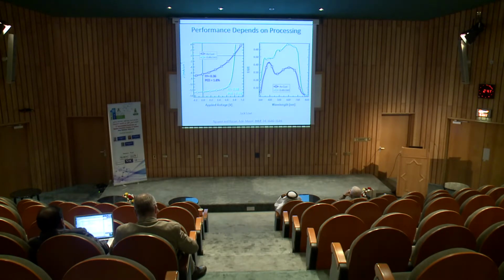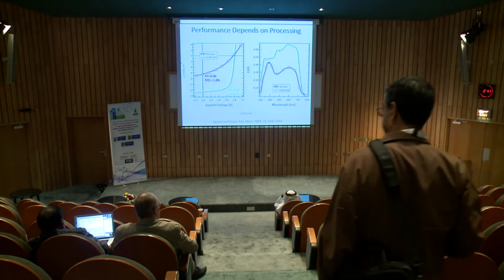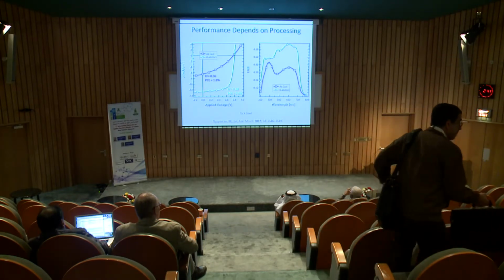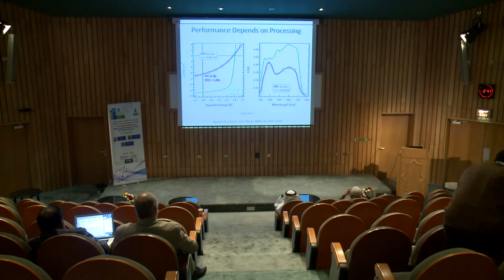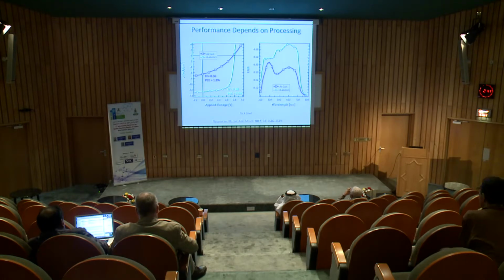So if you look at the blue curve, the as-cast device, you have only about 1.8% efficiency, and if you go to the 0.4% DIO processed device, you increase the device efficiency by a factor of 3. And the right-hand side shows the external quantum efficiency plot. You can see there are two peaks: the one at high wavelength, at about 600 nanometer, is the photocurrent generated by our donor material, the T1. And the peak at about 380 nanometer is the photocurrent usually generated by the PCBM.